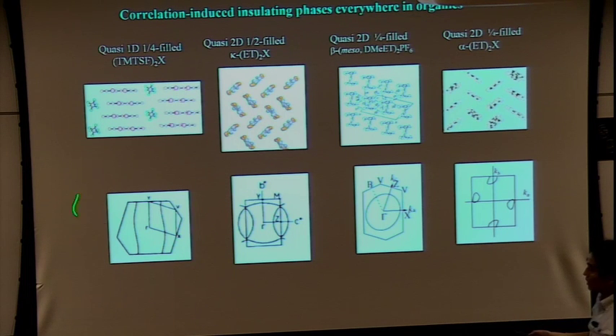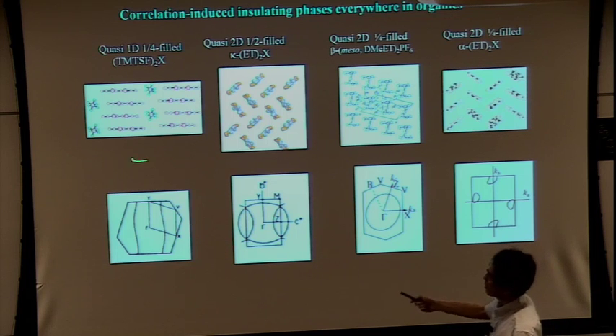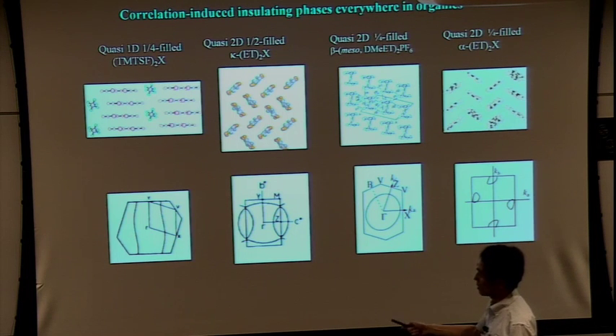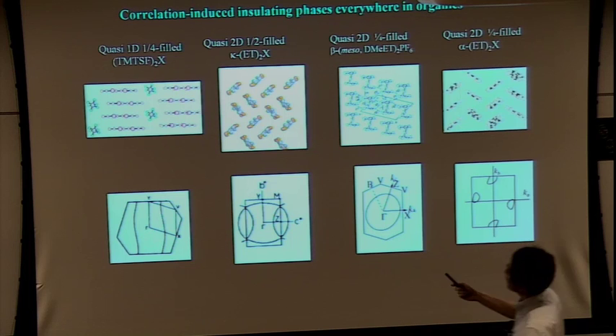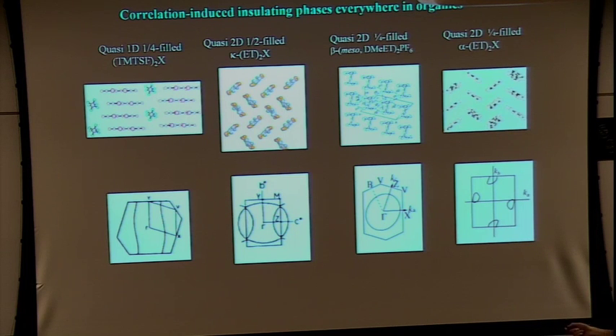In these materials, the Fermi surface is like this. Reflecting the one-dimensional character of the structure, an open Fermi surface with one-dimensional nature emerges like this. And these materials, as I said before, have a cylindrical Fermi surface, and this material is also cylindrical. And this material is a semi-metal, with a pair of hole pockets and electron pockets. Anyway, a very simple Fermi surface results from the tight binding calculations or first principles calculations of the band structure.